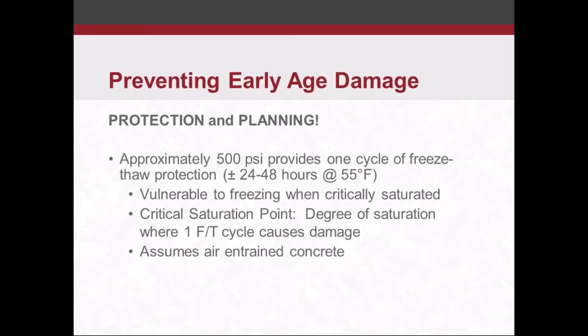So again, we want to make sure that we're protecting everything so that it can continue to gain strength. It's going to be very vulnerable during that critical saturation period where there's a lot of water in the concrete and the cement is starting to hydrate. That 500 PSI does assume that the concrete is air entrained. If you don't have air entrained concrete, you're definitely not going to get any kind of significant freeze-thaw durability, regardless of the strength.